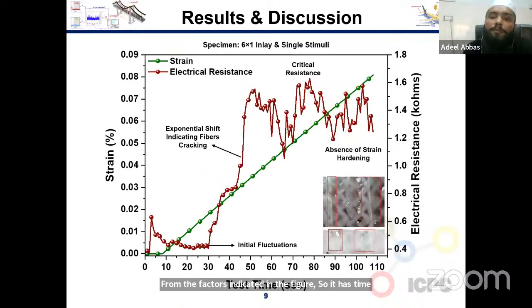Then in the second specimen of 6x1 inlay and of single stimuli layer, we can see that there is initially a small fluctuation area, and then there is an exponential shift due to fibers cracking. And critical electrical resistance values are difficult to identify in the 6x1 inlay pattern because there is a smaller amount of conducting yarn used in the 6x1 inlay pattern as compared to the 3x1.